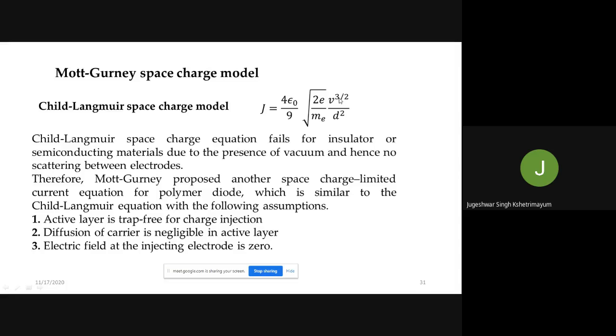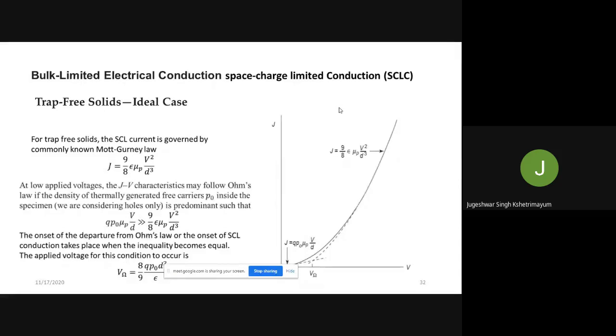So by assuming this one, he proposed another space charge limited current equation. Generally, assumptions 2 and 3 are still valid for most organic or polymer semiconducting materials, but assumption number 1, the active layer being trap free for charge injection, is further modified with a new version as the trap space charge limited current model, which will be discussed later. When there is no trap in the ideal case, then we call it Mott-Gurney.